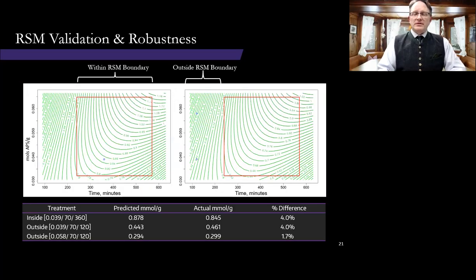Now, in order to prove the model, it requires a validation step. And so in this case, I picked 3 points. One landed within the boundaries of the model, as represented by this square plot, and then I picked 2 that were outside the boundaries of the model. The model predicted that this surface charge would be achieved, and the actual was this. And in all cases, we were within 4% error from the predicted versus the actual. So it really shows that this model has some robustness, contrary to what some research reported as being unrepeatable. So this is good for us.